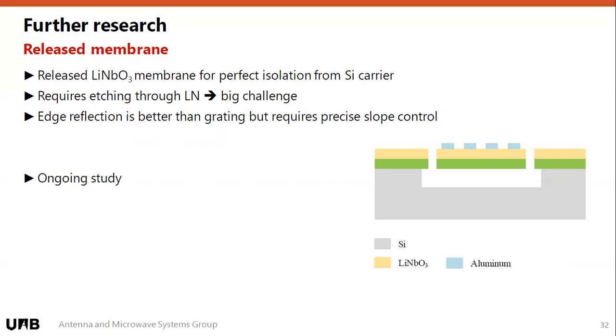However, the main challenge here is etching through the lithium niobate, because that's known to be one of the most challenging things to do for people working in this. The people who have tried commercial applications using this are now doing backside etching on the silicon because they don't really want to go into the etching of lithium niobate, because of a lot of byproducts and things. But I think Roger was trying something in this way, so this is an ongoing study also. Many things can be tested on this platform. And that should be all on my side.